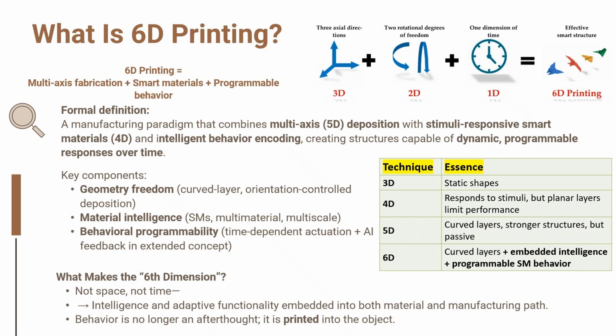6D printing is a manufacturing paradigm that merges three capabilities: multi-axis fabrication from 5D printing, stimuli-responsive smart materials from 4D printing, and the encoding of programmable behavior directly into the printed structure. In practice, this means that we are no longer just depositing material, we are depositing function. We control the geometry with curved layer, orientation controlled printing. We control the material through smart polymers, composites, and multi-material combinations. And we control behavior by designing how the structure responds over time to heat, stress, magnetic fields, or other stimuli.